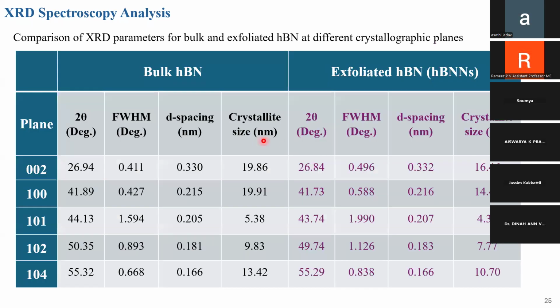And see, this is another area where I have done a comparison between the bulk HBN and exfoliated HBN. Take a look at the 2 theta angle of the planes of bulk HBN and exfoliated HBN. As I said already, the 2 theta value is very near to the bulk form. You can see the 2 theta values of the exfoliated are very well aligned with the values of the bulk HBN.